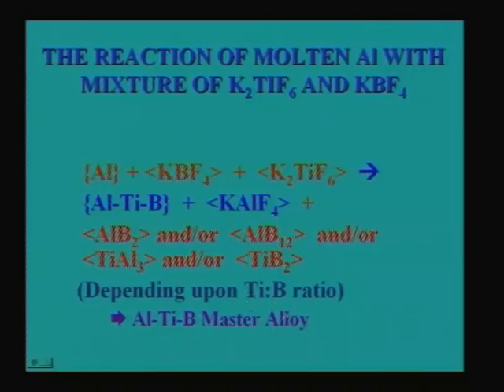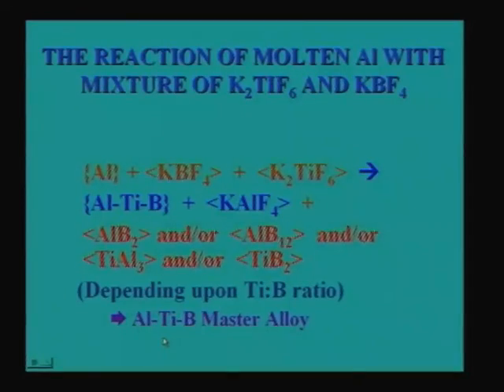One point is the Ti:B ratio, another the temperature, which is crucial, and the time of reaction, which is crucial. So all these have to be controlled, so that ultimately you end up in an aluminum TiB2 composite. So this is similar to making a grain refiner, aluminum titanium boron grain refiners, which we talked about earlier.